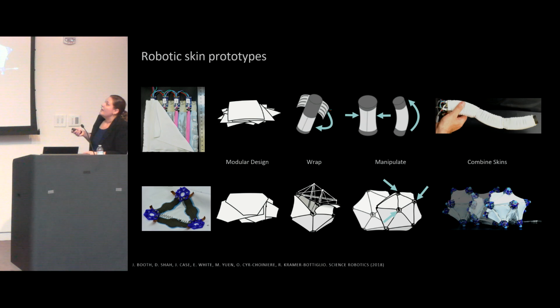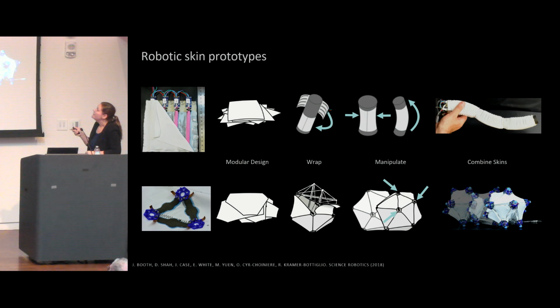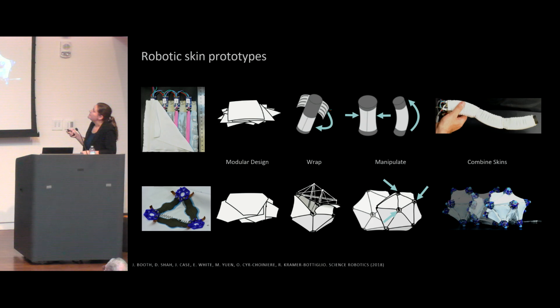And this is a parallel layout of components. So it's lendable to single curvature bodies, things like tubes or cylinders. So you can take these rectangular skins and wrap them around a cylinder of foam, for example. That's what's imaged here. And we can see that same kind of idea from the first ideation slide: wrapped in one orientation and sequentially contracting those linear contracting actuators, we would get a compression of the foam. And then if we take off the skin and reorient it 90 degrees, reattach it, we can get a bending of the cylinder, not of the skin, of the cylinder.